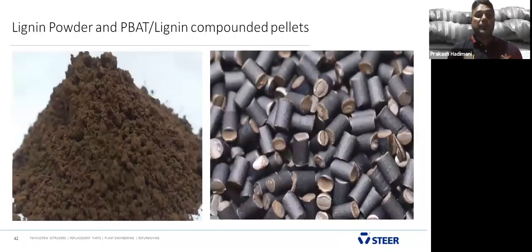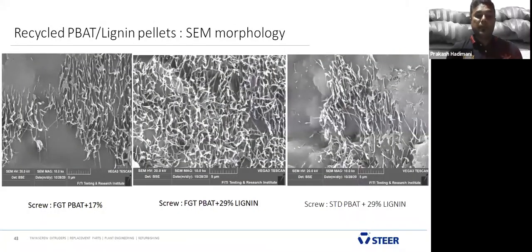These are the lignin powder with PBAT pellets. We observe smooth and uniform pellets. We also did a morphology study. On the left-hand side, PBAT with 17% lignin, we didn't see much distribution of the lignin particles in the polymer matrix, not uniform at 17%. But at 30%, all the lignin powder is distributed evenly, completely homogeneously dispersed in the PBAT. That's why we could manage higher mechanical property at 30%.